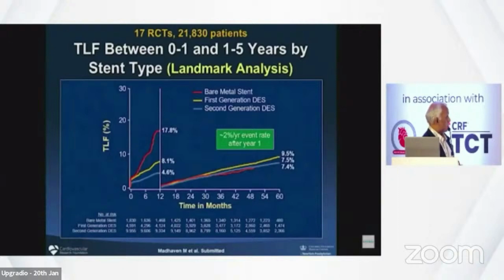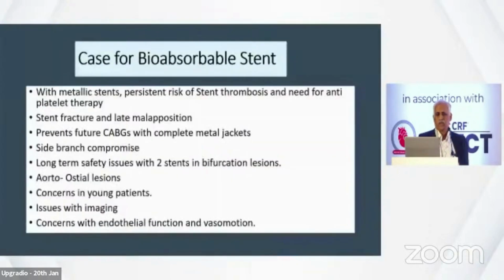But after 1 year, there's not much difference. Watch over the stent, after the 1 year landmark analysis, there's nearly 2% event rates per year. So, stents are not suitable in the long run. With metallic stents, there is persistent risk of stent thrombosis and need for antiplatelet agents, a case that we want